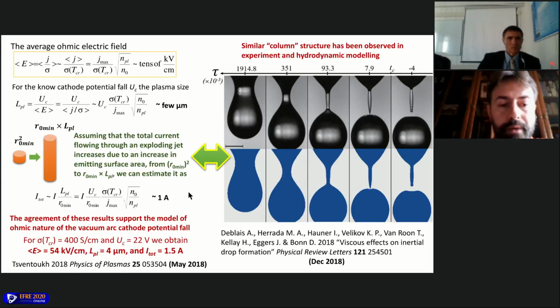In fact, we can also estimate the total current. So we can use some geometrical considerations. If we have an explosion of the neck with a small radius and a longitudinal size of a few microns, then from simple geometry we can estimate it to be about 1 ampere. That corresponds to the observation of threshold current in a vacuum arc. So if we use this model with the explosion of liquid metal jets, we can estimate threshold current. And there are some certain estimations for the conductivity of the media and for the cathode fall, just for example.